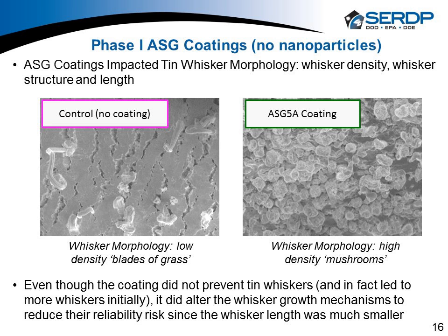But what we found, and thank goodness our co-ops, when they're working on this, young minds do some neat things. They looked at it and they looked at these coatings. And you can see here on the right the ASG5 coating. The whiskers grow through this, and they grow through this like chia pets. They're just everywhere. But they're really short, and they look like little button mushrooms. As opposed to the whisker behavior here on the left we were seeing on our control specimens that had no coatings. They were growing long whiskers. We talk about them as blades of grass, long enough that they could go short. Versus my little button mushrooms, they're not going to short to anything anywhere.